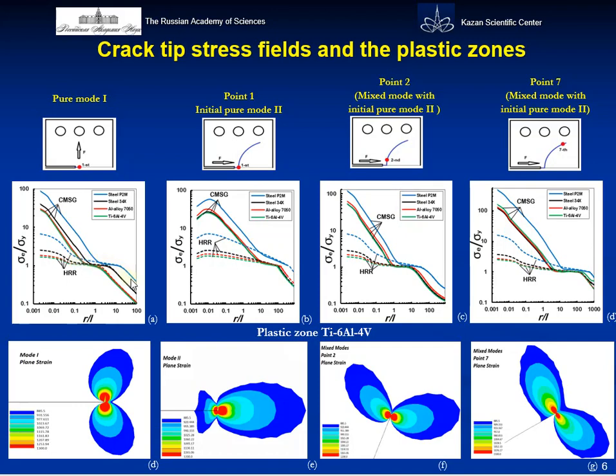The effective stresses on the crack extension under gradient plasticity are an order of magnitude higher than under the classical HRR theory of plasticity. As we move away from the crack-tip, the effect of gradient plasticity disappears, and the solution gradually moves to the state of a classical singularity of the HRR type. The bottom row of figures demonstrates the behavior of plastic zones at the crack-tip according to the strain gradient plasticity solution for several successive positions of the crack-tip on the curved path of its growth. It can be noted that as the crack grows, the shape of the plastic zone gradually changes from pure mode 2 to a state close to mode 1.